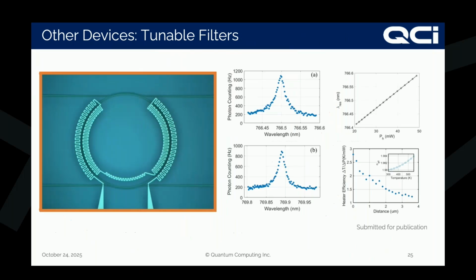For tunable filters, the previous one that I showed you was at a wavelength of a little bit more than 1550, larger than that. So that's in the infrared or near infrared. But here we have shown it at a different resonant wavelength around 766 nanometers, and a similar thing can be applied by applying thermal power. We can tune this filter very well at a wavelength that is closer to the visible. And by the way, that's another feature of thin film lithium niobate, that it has a very wide wavelength bandwidth through which light can propagate.